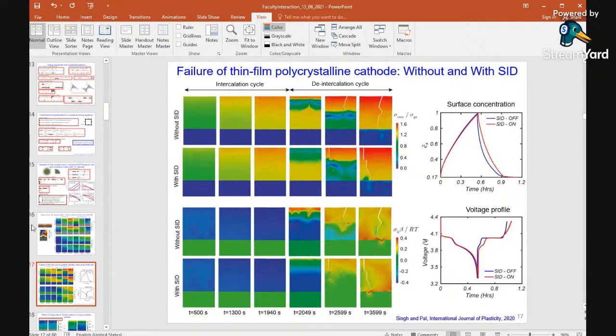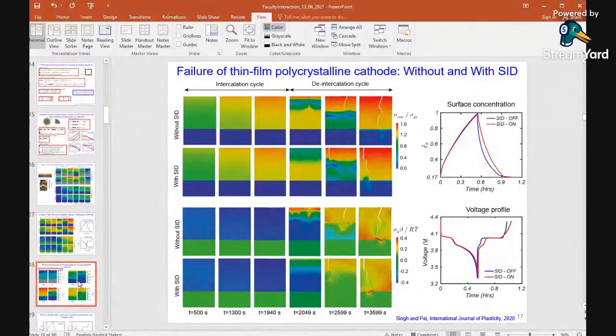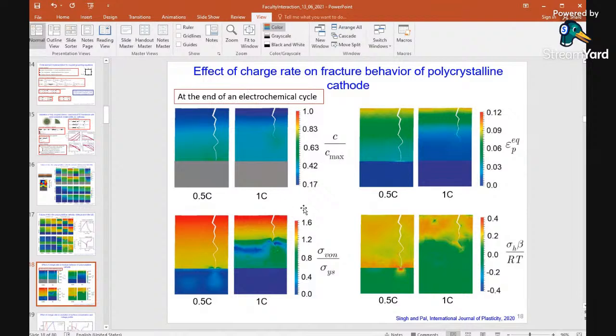And again, the voltage also, we have seen that there is an impact on the voltage side, how that is connected. So we have performed a detailed study, then we studied the charge rate, how the charge rate is affecting the crack propagation. We see that when the charge rate is faster, the 1C charge rate, the crack remains on the top level. It doesn't enter into the system. But when the charge rate is lower, the crack goes till the end.